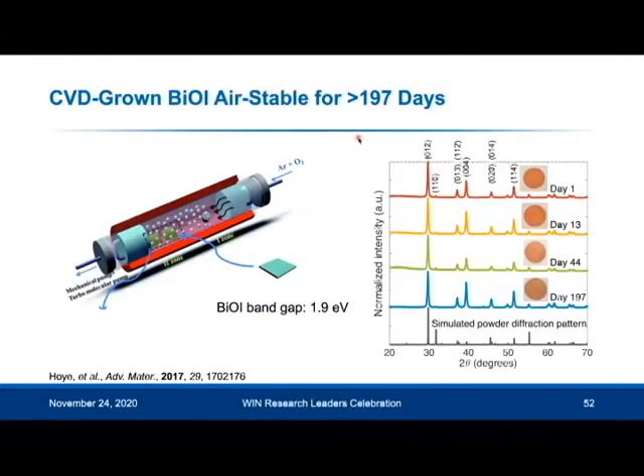So we grew bismuth oxyiodide by CVD using this tube furnace, and it has a band gap of 1.9 electron volts, so that results in this red appearance that you see here. And we left these films in ambient air for 197 days, and we found that it stayed the same. So it was stable over this testing period. Now contrast that to the perovskites. If I were to leave methylammonium lead iodide in air in the same conditions, it would degrade within 5 days. This material is at least 2 orders of magnitude more air stable than the perovskites are.